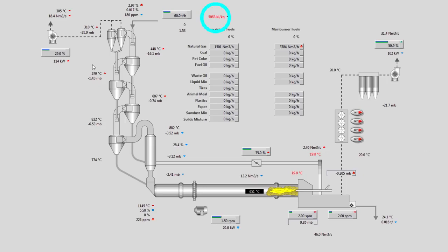High thermal consumption compared to the nominal value, but we need it to get our first clinker. You see as well we have 28% of fuel in the precalciner, while at full capacity we should run at 60%.